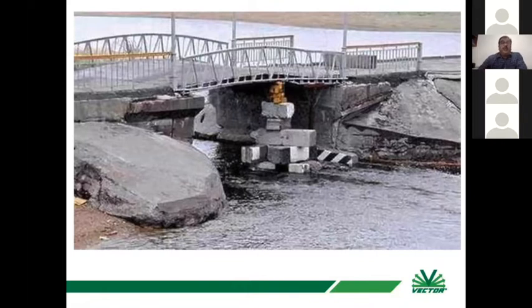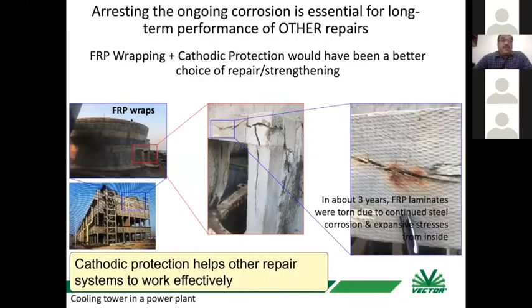Even if we have a standard practice of structural strengthening using CFRP wrap, and when we design CFRP, even ACI 440 says that unless you take care of corrosion of the RCC structure, which is going on inside the structure, you cannot do strengthening using a CFRP system. And it fails. We had various examples, which we can see on the screen.